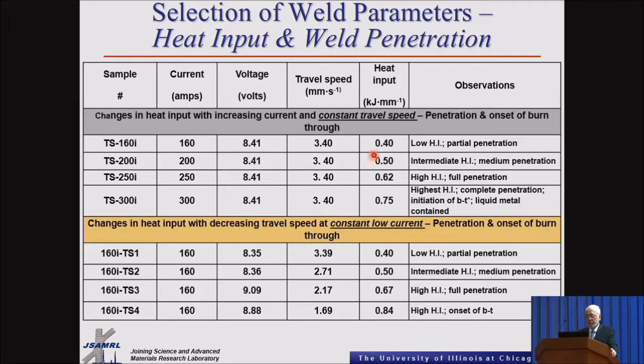And you can see here the heat input. So we have a change in heat input, and then we try to do some assessment of the welds, looking at partial penetration, intermediate penetration, and then full penetration. For the highest heat input, you can see the onset of burn through, in which we had some partial melting, but again the weld was contained. The same thing in this case: we fixed the current and changed the travel speed, as you can see here. We slowed down the travel speed, so again we were increasing the heat input.